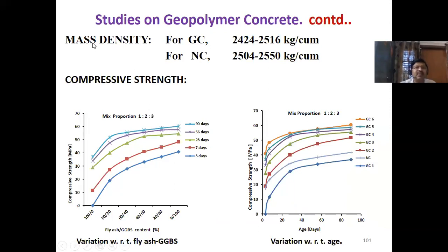And this is the strength development. The density of geopolymer concrete was 2424 to 2516, and normal concrete is 2500 or so. That means almost the same. So the density, the specific gravity of both concretes, geopolymer and normal concrete, is almost the same. In fact, geopolymer will be marginally less, of course, not too much. And this is the compressive strength development. As the GGBS content increases, strength increases. And this is how with age there is an increase in strength, right?